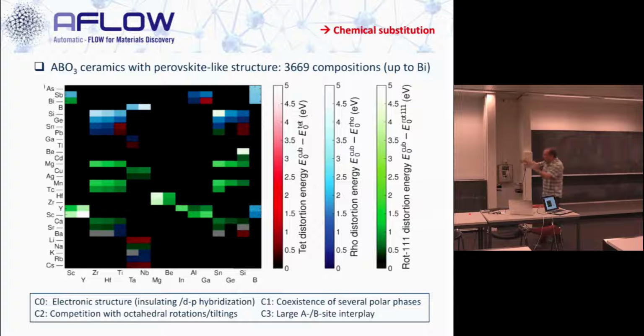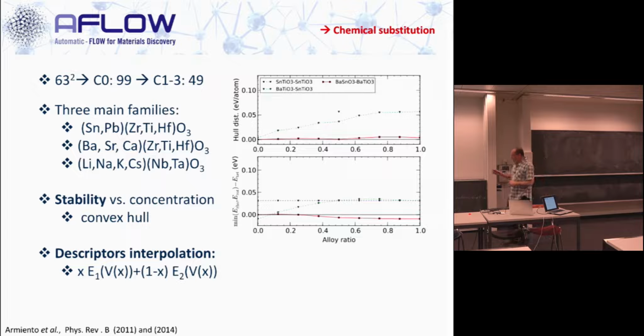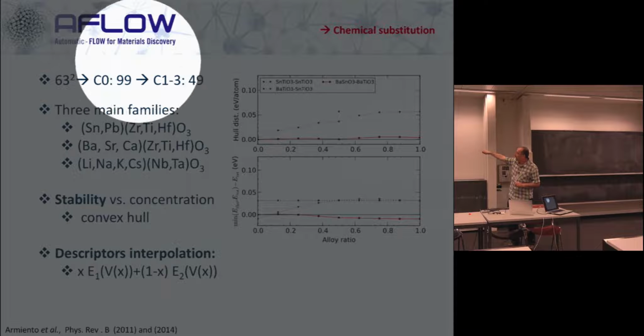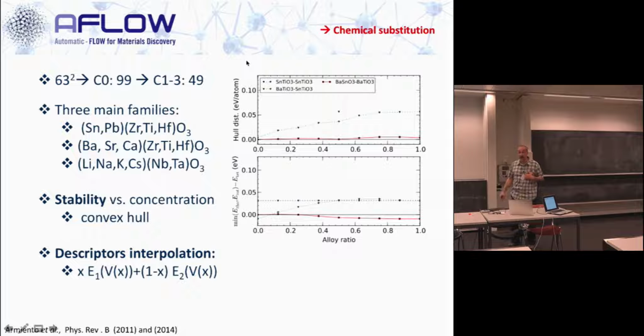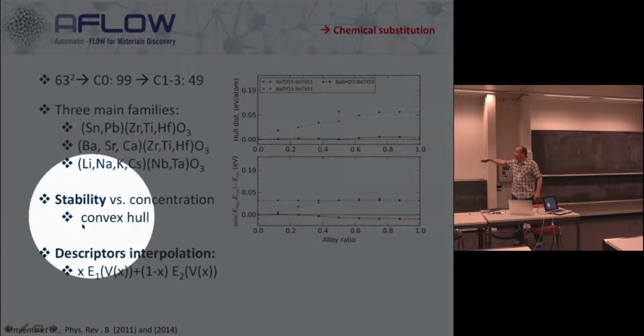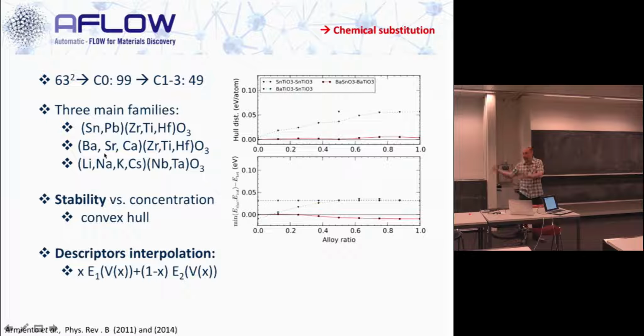So by doing several of these maps, we filter out, according to C0, C1, C2, C3, all the possible perovskites. And so the configuration space was decimated, right? We start with almost 4,000, and then after applying criterion number 0, we got to 99, okay? And then out of the 99, with criterion number 1, number 3, we get to 49 compositions. So the good thing is that, out of all this, we distill 3 families, and these are the 3 families that were known at the time.